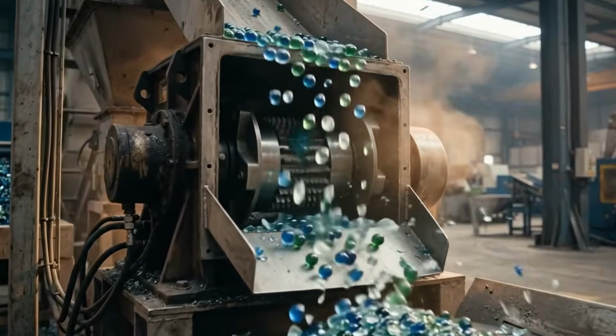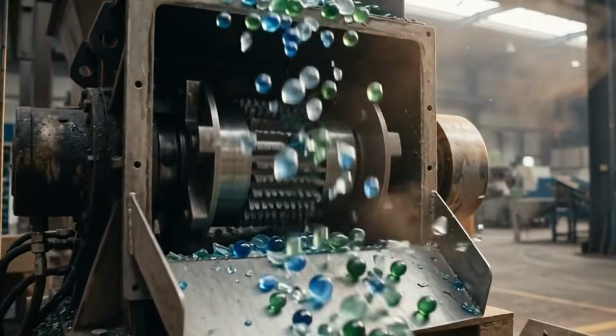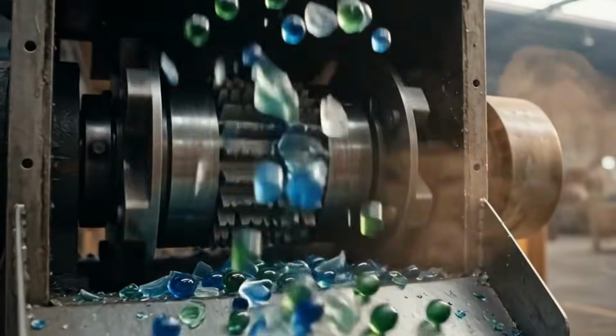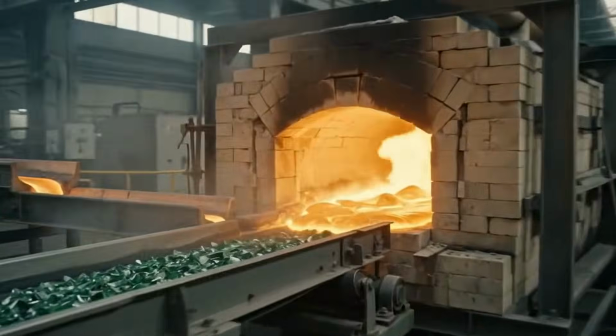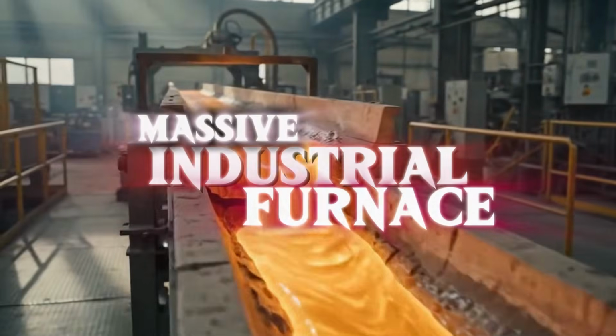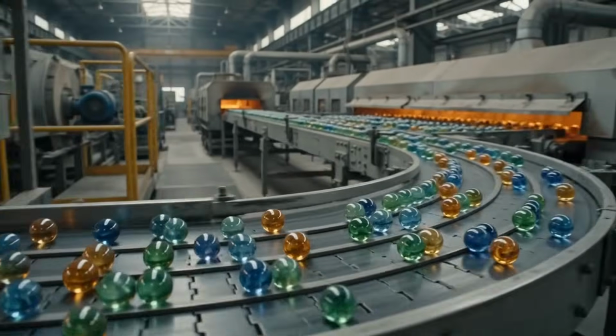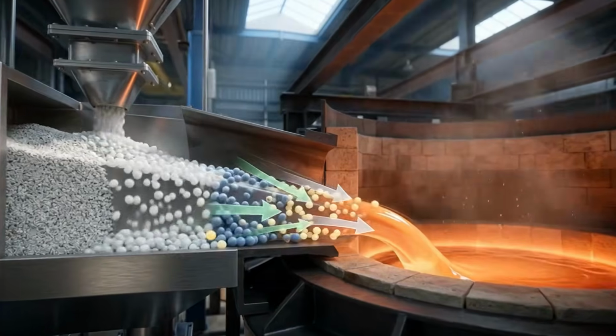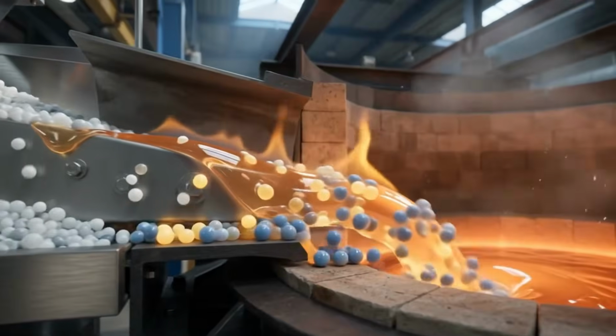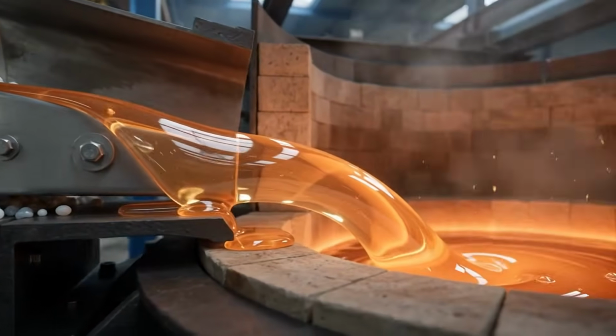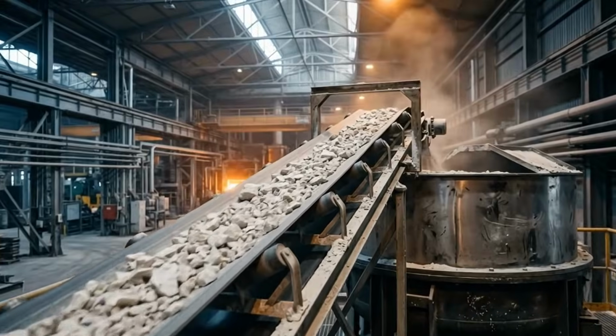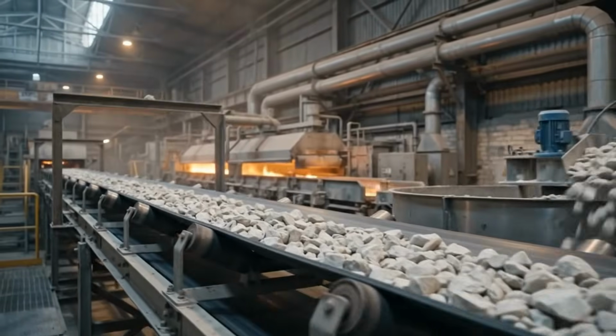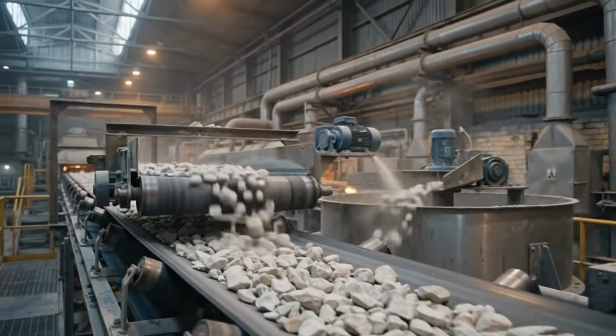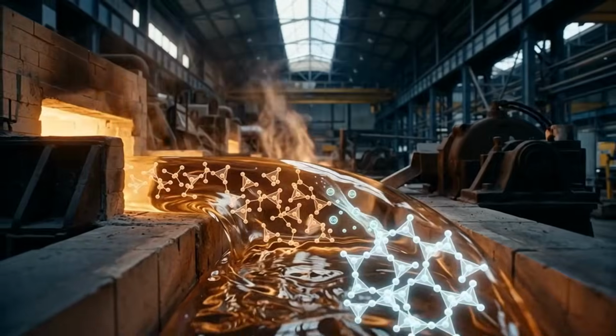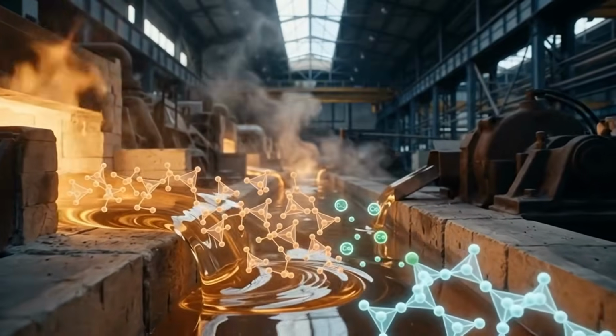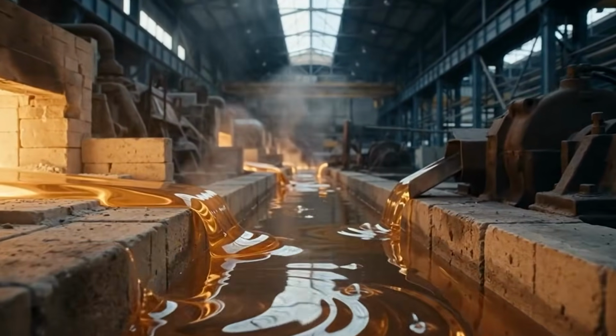Now, the moment you've been waiting for. The raw materials, silica, soda ash, limestone, and often recycled glass are loaded into a massive industrial furnace, and that furnace is cranked up to temperatures between 1200 and 1270 degrees Celsius. To put that in perspective, steel melts at around 1370 degrees Celsius. We are melting glass at temperatures that would liquefy metal. Inside that furnace, something almost magical happens. The sand, that rough, granular, opaque handful of earth, begins to dissolve. It transforms into a glowing, molten liquid. Thick, radiant, moving like slow lava.